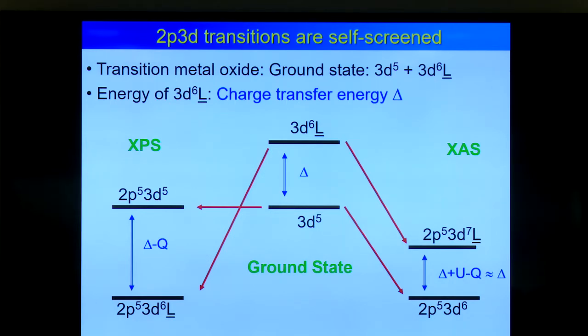So X-ray absorption, optics, EPR, they are neutral, so you can do crystal field calculations because you can neglect charge transfer. That's completely different than ionizing experiments like photoemission and Auger, because then you take out an electron from the system, the core hole has to be screened, and the screening is done by moving an extra d electron there. So now you go from d5 to 2p5 to d5, but now the excited state moves down by the core hole potential Q, which is 8-9 electron volts, to below the d5, and now you need these two configurations. If you forget about this, you can never describe photoemission.